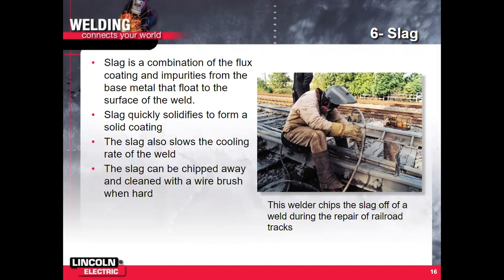So if we're working on a deep joint, where we have to put 6 passes in there total to fill it up, the first pass goes in okay, the second pass goes in, there's a bunch of junk in there, and you kind of chip it off and you weld over it with the 3rd, 4th, and 5th passes. So that stuff is stuck in the middle of that weld. Kind of like jelly in the middle of a jelly donut, right? You don't see it from the outside, but it's in there. That's what we don't want in a weld. That's going to take major amounts of strength out of that weld, and it's just not good practice at all to ever have any junk in your weld. We want solid weld material the whole time.